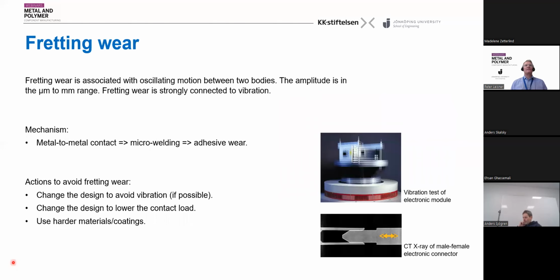The phenomenon fretting wear is always associated with vibration, meaning that you will have small oscillating motions between the two contact bodies. The amplitude could be in the size of micrometers or up to millimeters. This is usually related to machinery, cars, or airplanes, where you have vibrations, and this is tested on vibrators. This is from a test lab where an electronic module is vibrated, supposed to see that components are actually staying where they should stay, but you will also be able to find out if you have wear problems or contact problems due to fretting wear.